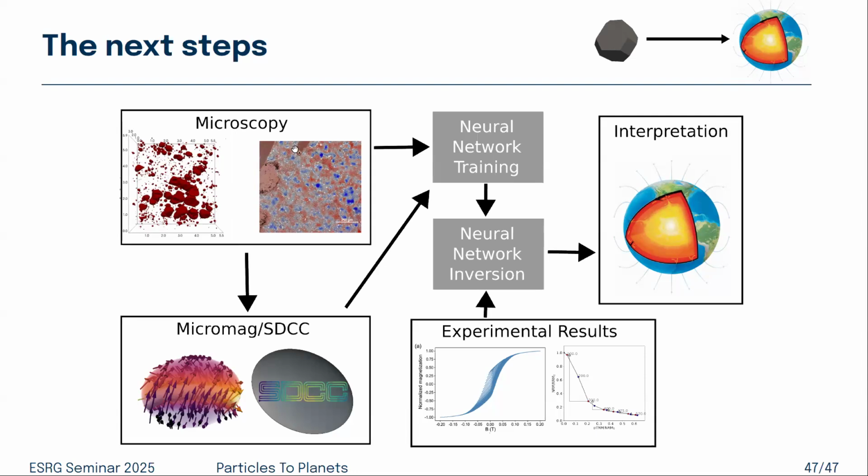I've actually done some work where I measured one of these things in between steps in an experiment to see how things change, and then identified regions where things were behaving well and badly. Then you can go in and say, okay, which grains are directly responsible for that bad behavior? So there's some quite interesting stuff that you can do in microscopy. Does that answer your question about state of the art? Yes, thank you. Time permitting. Yeah.